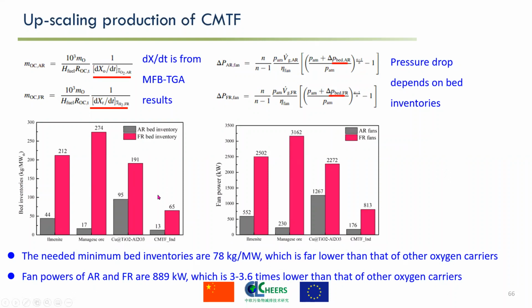The total needed bed inventory is 78 kilograms per megawatt. This bed inventory is likely underestimated, just because we calculate the FR bed inventory by the hydrogen conversion, not according to the coal or char gasification. But at the same conditions, the bed inventory is far lower than that of other oxygen carriers: ilmenite, manganese, and copper. Also, the fan power is 3 to 3.6 times lower than that of other oxygen carriers.